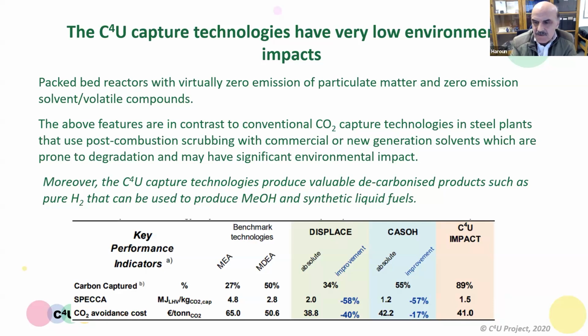The percentage of carbon which is captured is expected to be up to 89%. SPECCA 1.5 megajoules per kilogram of CO2, and the CO2 avoidance costs is 41 euros per ton, as compared to benchmark technologies, which can vary between 65 to 50 euros per ton.